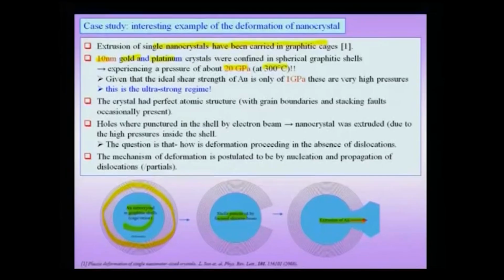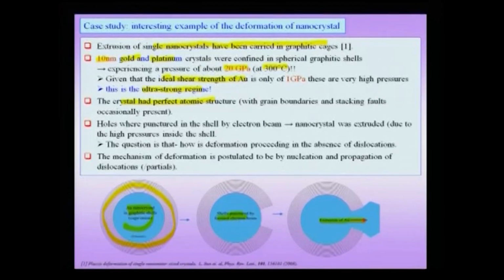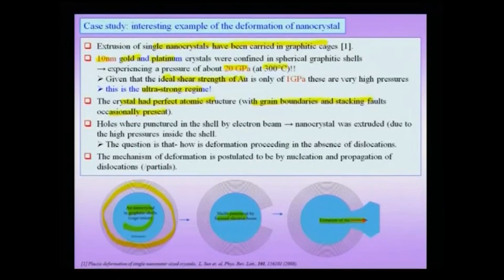So, this is extremely high pressure, which is what this small carbon onion cage is able to impose on this gold or platinum nanocrystal. Given that the ideal shear strength of gold is only about 1 GPa, you see that this regime can be actually called the ultra strong regime, and therefore, you are actually extruding or keeping the material in the ultra strong condition under this kind of a carbon onion shell. The crystal had a perfect atomic structure with grain boundaries and stacking faults occasionally present. So, the gold crystal, when you observe it under electron microscope, occasionally you do see grain boundaries and stacking faults, but apart from that it is a perfect crystal, and because of this high pressure the lattice parameter is actually smaller than the bulk lattice parameter. When holes are punctured by an electron beam, the nanocrystal was extruded due to the high pressures inside the shell.